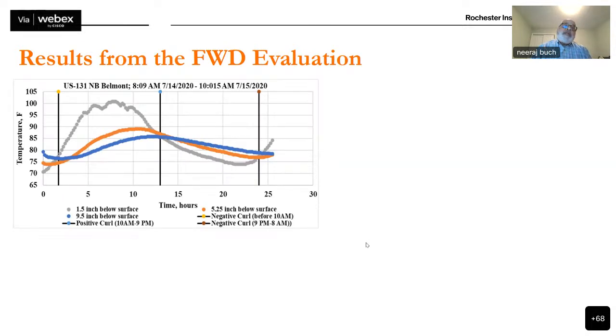So it's not theoretical. We actually demonstrated this in the field. What you're seeing here, along the x-axis, is time, and along the y-axis, temperature in degrees Fahrenheit. The three curves you are seeing are from thermocouples where we actually measured the temperature gradient. The gray line is a thermocouple placed 1.5 inches below the surface. The blue line is the temperature measured 9.5 inches below the surface. And the orange line is about 5.25 inches below the surface.